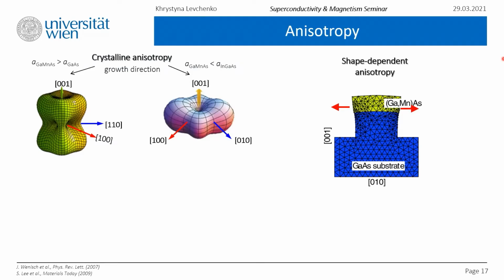We already established that growth conditions are crucial for the material's parameters. So let us look into the anisotropy. Depending on which buffer we choose, for example, gallium arsenide with lower lattice parameters than the top layer, or indium gallium arsenide with higher lattice parameters than the top layer, we may arrive at a different set of easy magnetization axes. Here they are indicated by the deepest energy minima. Easy magnetization axes are formed to minimize a carrier's total energy needed to preserve the ferromagnetic state for a collective macroscopic magnetization of manganese moments. This is driven by the Fermi level position in the valence band or magnetization-dependent exchange splitting. Thus, it's dependent on the hole concentration and the temperature.